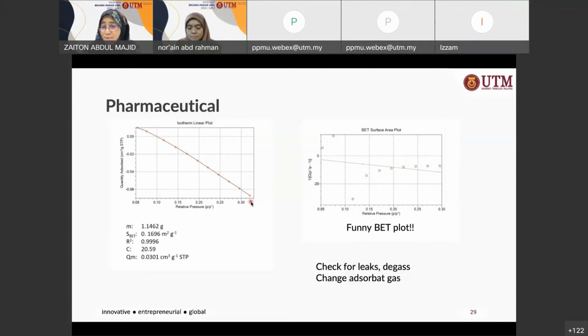Maybe the adsorbed gas is not suitable, right? Look at the surface area, it's 0.1696. The mass is about 1.1462 gram. R square is 0.9996. C value is positive, okay, but still, this is not right. And the BET surface area plot, the BET transformation plot, is also not right. So you have to check for leaks, or maybe you have to change the adsorbed gas.